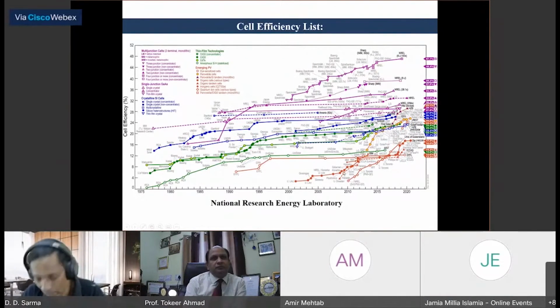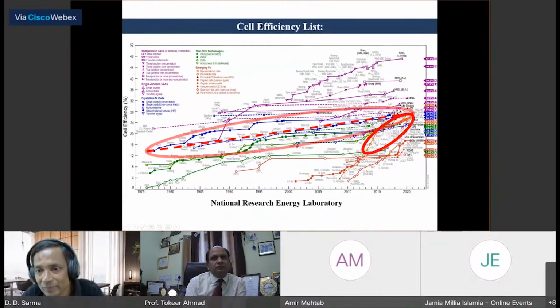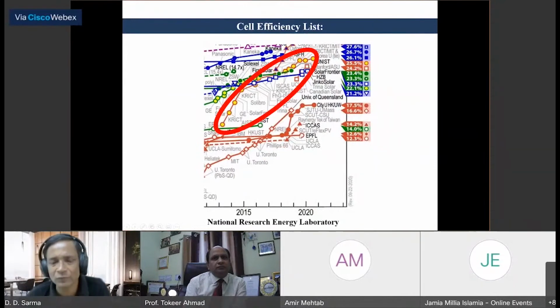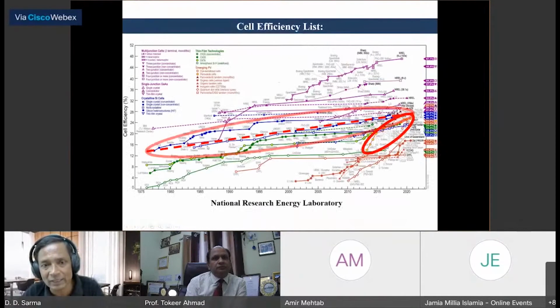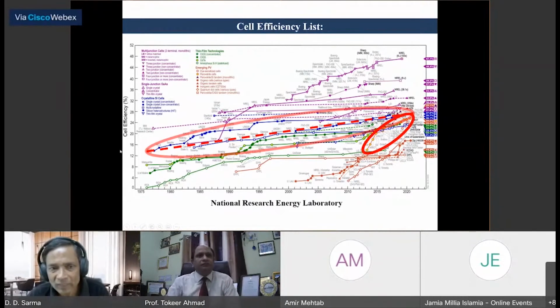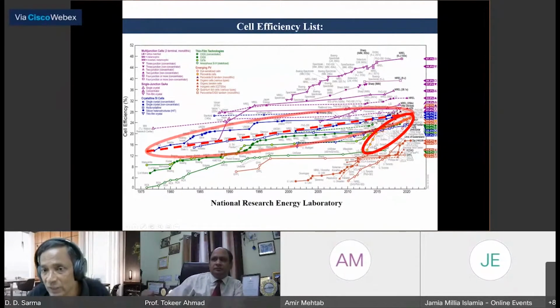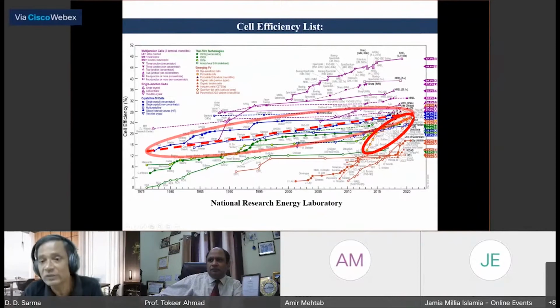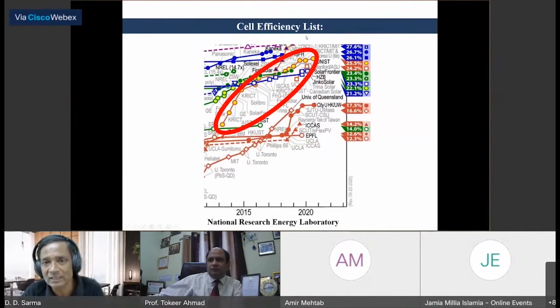Now, I'm going to show you another material, this wonder material, which is here. Its properties were discovered essentially around 2010, but in the last few years, it's gone up very quickly, and you can see I've expanded it here. In this slide, I'm comparing it with the silicon technology. Silicon technology took 40 odd years to increase the efficiency, which this particular material has achieved in less than 10 years, and has come to an efficiency equal to the silicon technology. So it's really spectacular growth.